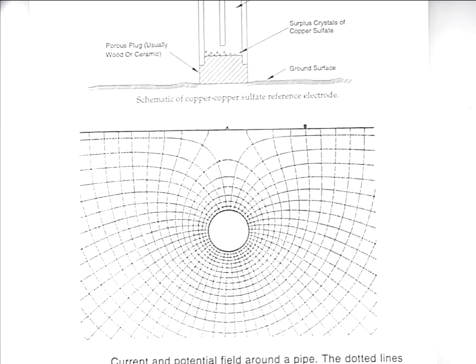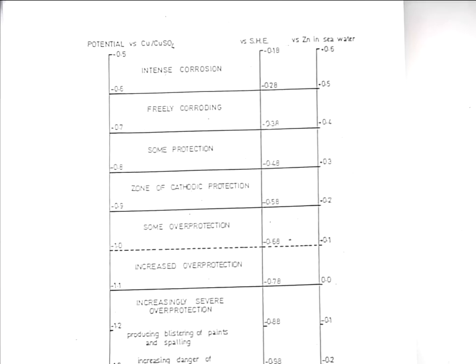The point is, when we get into our zone of cathodic protection, where we're happy that the steel is not going to corrode, that's 0.9 volts against the copper sulfate. It's actually only about 0.6 against the standard hydrogen, and it's only minus 0.2 against the zinc in seawater. So you've got to make sure that you quote the right reference electrode so you know where your values are coming from.